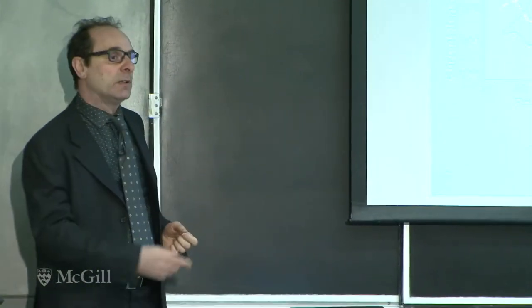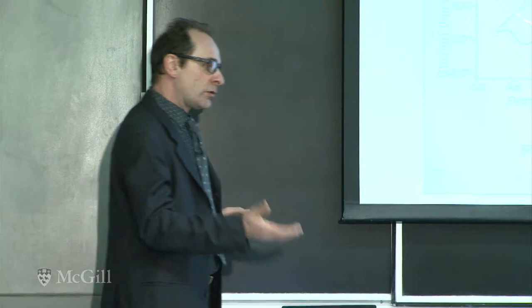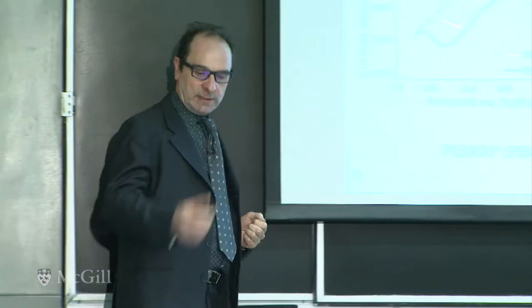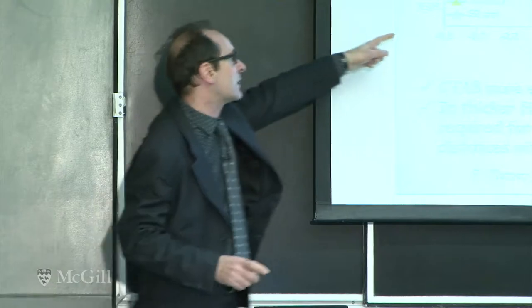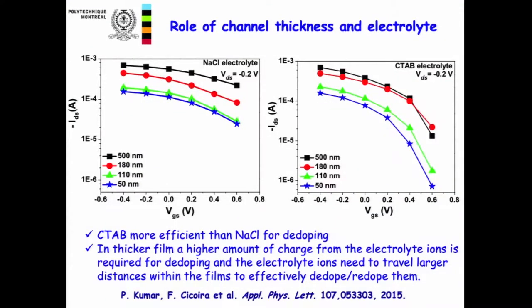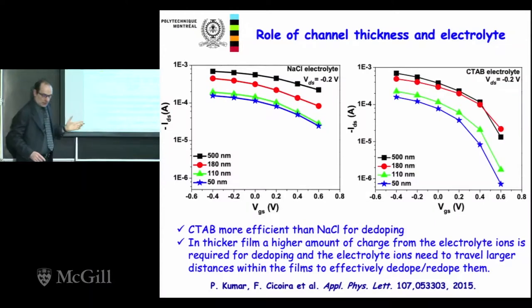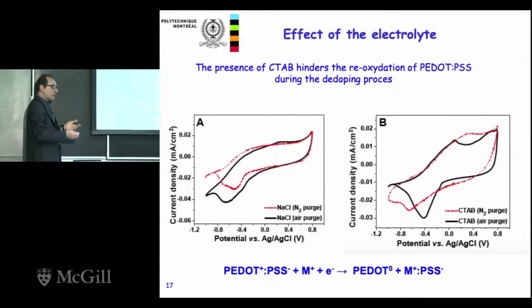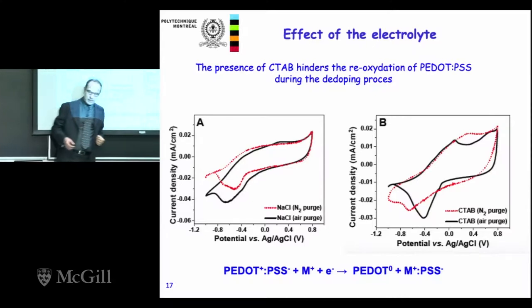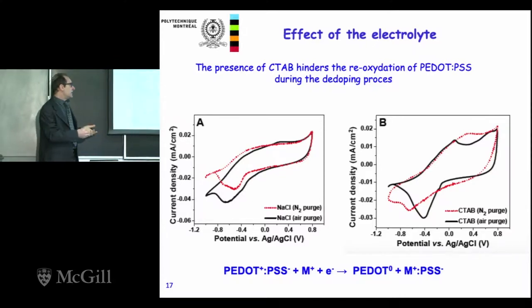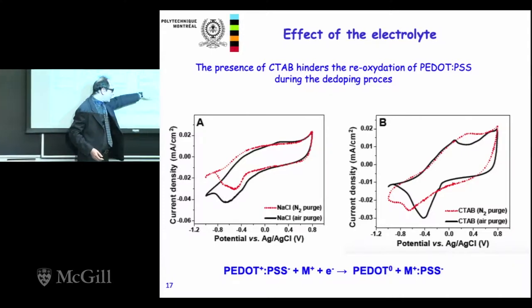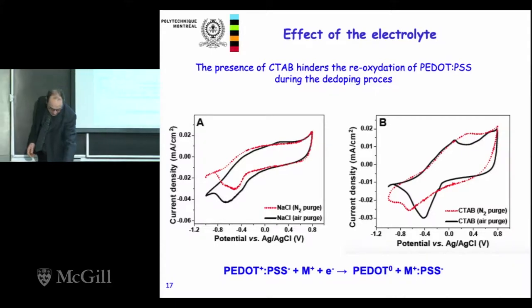And when you reduce the material while your transistor is working, what happens is that the oxygen in solution reoxidizes the material. So you cannot get a very low off current, as you see here. You are not able to go down with this value because the oxygen reoxidizes the material. The oxidized state is conductive, so you cannot really decrease the current here. But what we found out is that if we use the surfactant, we decrease the oxygen content in the solution. This is reported by several papers. And by decreasing the oxygen content in solution, we can also prevent this reoxidation of the material.